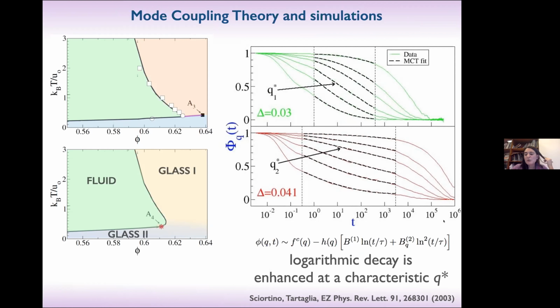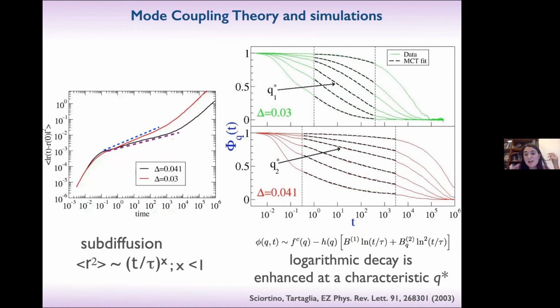And you can imagine that these were very, very long simulations that we did a very long time ago. I think we waited several months to obtain these results. But these results really verified the existence of this higher order singularity and the onset of the anomalous dynamics. And similarly, we monitored also the mean-square displacement. For the 3% case here, you have subdiffusive behavior in this window. For the one that corresponds to the higher order singularity, this extends as it should, and you find subdiffusive behavior for many, many decades as well. So this, I think, was a very strong confirmation coming from simulations that the predicted scenario of the mode-coupling theory was working, and it opened up really a lot of activity on this.